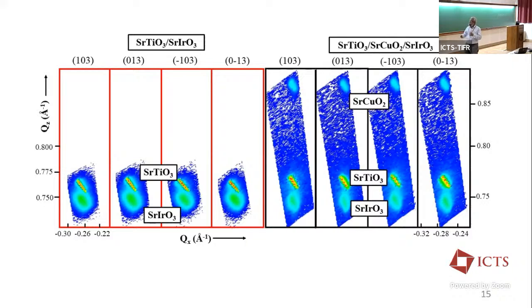Because the electronic property of SrIrO3 is very much prone to distortion, we wanted to really know that whatever we are seeing in our transport is not because of distortion. So we looked into reciprocal space mapping to see whether there is some distortion or not. We see that along all four directions of 103, the Qx and Qz values are similar, and similar is the case when it is grown on top of SrCuO2. So in both cases, we do not see much distortion.